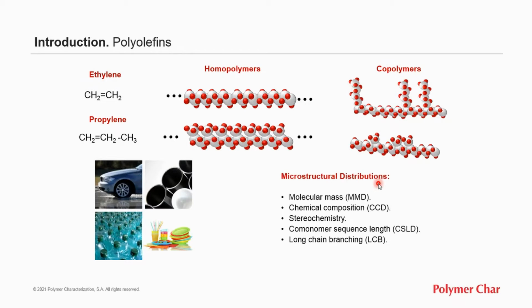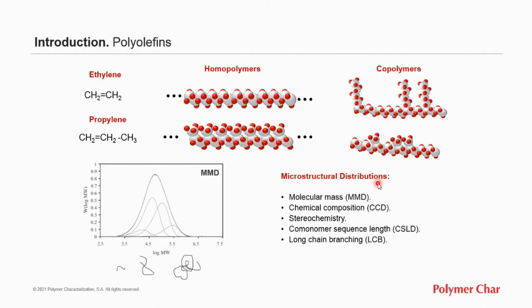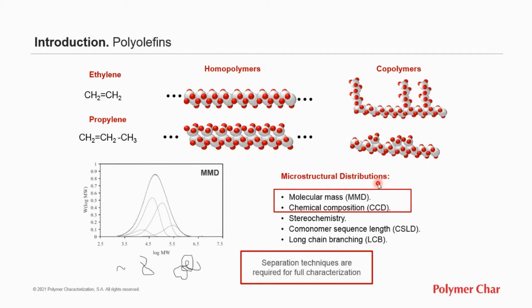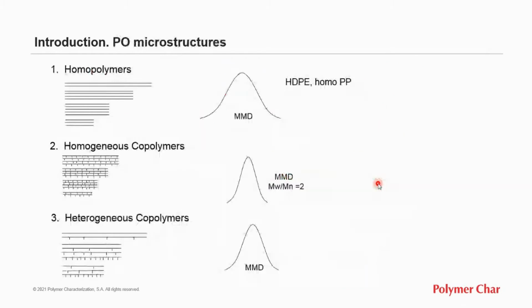That versatility is due to the polyolefin different microstructural distributions, which can be controlled, such as molar mass distribution, chemical composition distribution, also stereochemistry, comonomer sequence length, long chain branching. Most important are the molar mass distribution and chemical composition distribution. The average properties measured by spectroscopic techniques are not enough to define a given product. So separation techniques, which can fractionate the polymer according to some microstructural feature, are required.